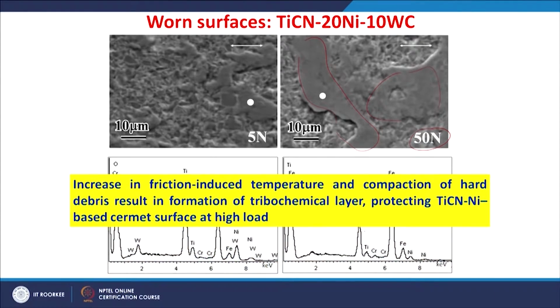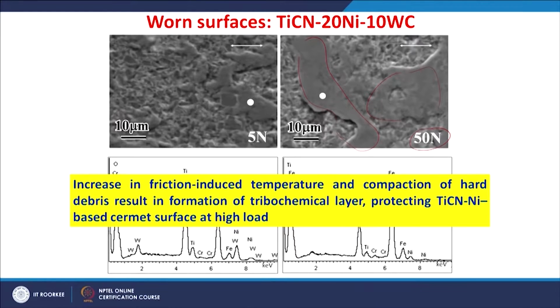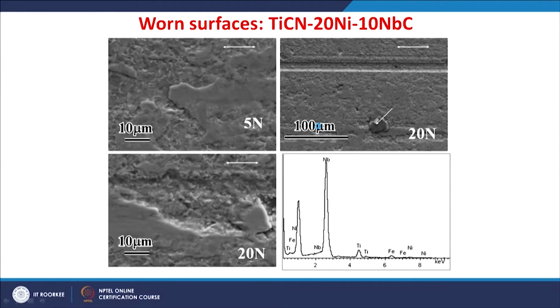So, the increase in the friction-induced temperature because of the higher loads, and also the compaction of those debris, result in the formation of such a layer, and this layer actually protects the underneath surface. So, that reduces the wear or the friction. So, these are the worn surfaces for the titanium carbonitride nickel niobium carbide cermet.